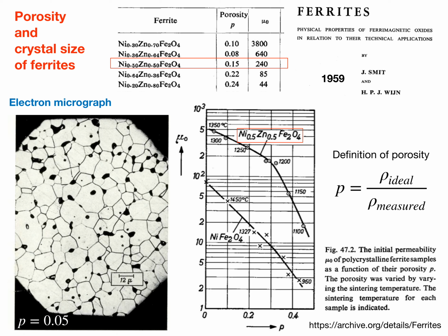The figure at the center, also from this book, figure 47.2, shows the dependence of the initial permeability, quoted here as μ0, as a function of porosity, for nickel ferrite and also nickel zinc ferrite. It is apparent that over this range of porosity, the permeability changes from 20 all the way up to 500. The micrograph also indicates the size of the crystallites of the polycrystalline material. It is well known that permeability also depends on the crystal size. Porosity and crystal size are the two main reasons why permeability can vary drastically for a certain type of ferrite.